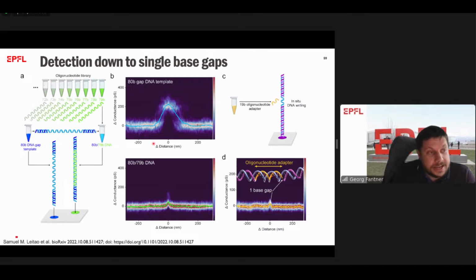And indeed, so this is the curves that we get when we're measuring just the bare gap region with 80 base gaps, so a very strong signal. But even with a single base gap, we still very clearly can see the one base missing. And so we really can say that we have a single base gap sensitivity. And the nice thing is that we can actually do this now in a repetitive fashion. So we can do the measurement first with the bare strand, then we can add the complementary strand and really see that it's really a single base gap that we're measuring.